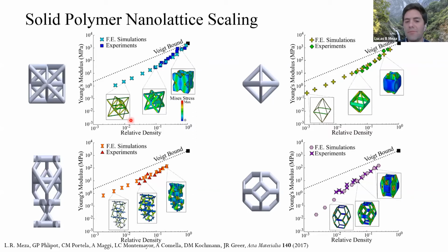the beams themselves weren't the dominant factor controlling the mechanical properties—it was actually the nodes. So here, when you make very dense structures, the nodes take up a considerable volume fraction of your material, and you can't consider this as a beam-based structure.